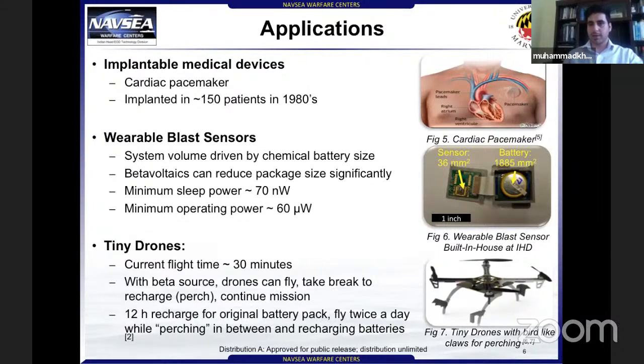In some applications where a betavoltaic power source cannot directly provide power, it can be used with lithium-ion batteries. In the case of a tiny drone used for surveillance purposes, its current flight time is approximately 30 minutes. If we put a beta source together with a lithium-ion battery, the beta source, which is a constant power source, gives you power 24/7. It can charge the lithium-ion battery. Then you can have your drone fly, take a break to recharge, and then continue the mission without coming home, without coming to the station. As you can see here, this tiny drone has bird-like claws for perching.